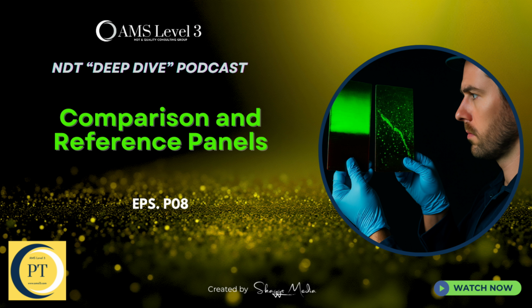The penetrant gets drawn into the much larger developer particles. Instead of being packed tightly in a tiny crack, the fluorescent molecules are spread over a larger area within the developer. This larger surface area interacts more effectively with the UV light, making it fluoresce much more brightly than it would down in the crack.